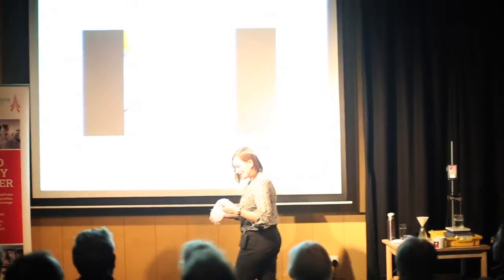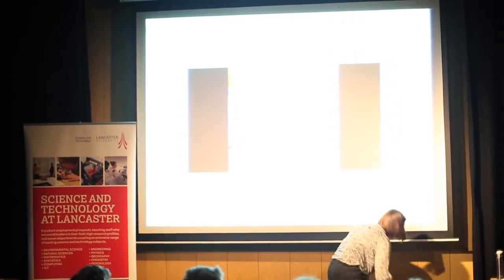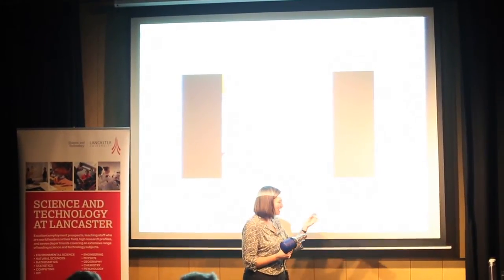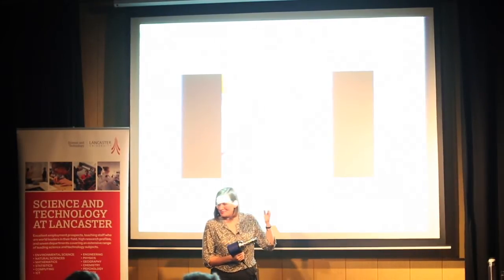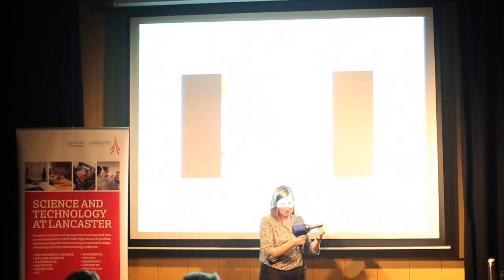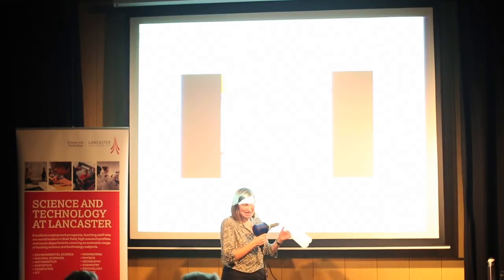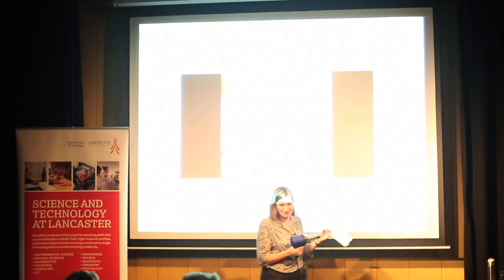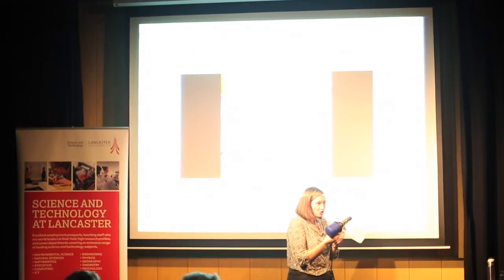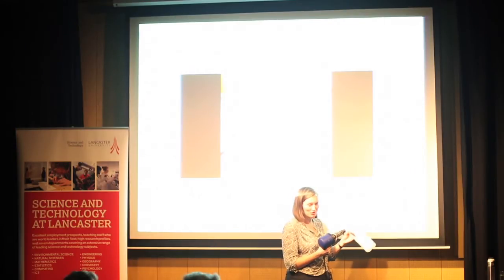So now let's see what we can do when we melt it. I'm going to heat this carton with this heat gun. I can't talk while it's on because it's quite noisy, so I'll explain what I'm going to do. Now the melting temperature of polyethylene is about 120 degrees. So we're just going to melt a very small corner here. And then I'm going to blow into the neck and demonstrate one of the industrial methods of processing polymers, which is where we melt the polymer, but because it's so viscous, we can then blow it into the shape we need. It's called extrusion blow molding.